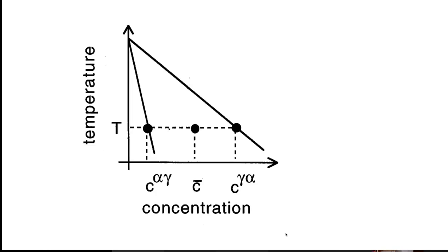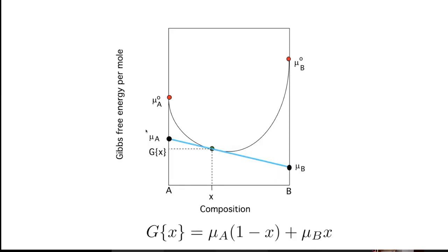The fundamental principle we use is local equilibrium at the interface — that the compositions at the interface are given by a tie line of the equilibrium phase diagram. Although the concentrations in ferrite and austenite are different, the chemical potential of carbon in austenite equals the chemical potential of carbon in ferrite when we choose these values. Therefore there is no tendency for carbon to transfer between the two phases.